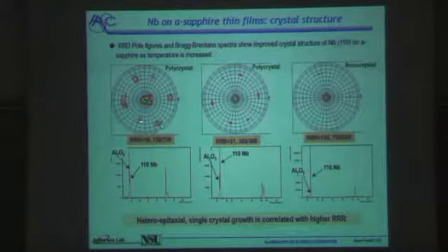What does one see? One sees the pole figure showing the 110 with the so-called twin symmetry. You see these 2 extra nodes. They aren't just 2, there are actually 4 of them, with the other 2 blended into these 2. And you see they're sort of diffuse in this psi direction, which indicates a sort of polycrystalline structure in the film. When you get up to the high temperature and anneal this thing as you're coating it, you find these 4 dots are very tight, central peak, twins are absent. You've gone to a monocrystalline structure.